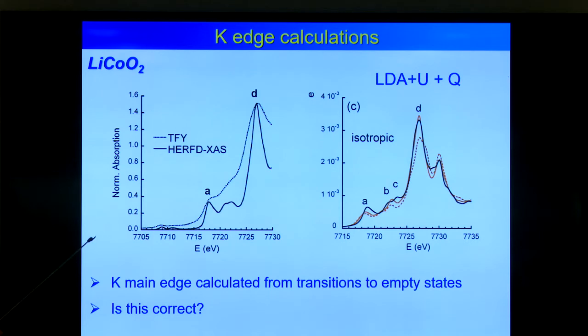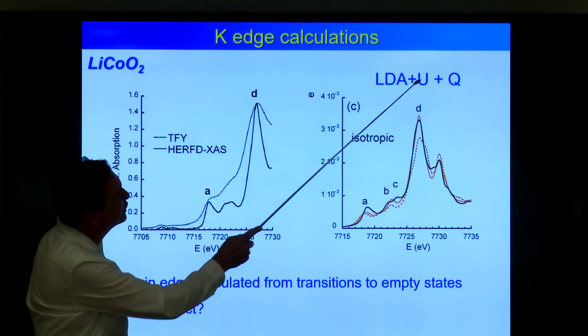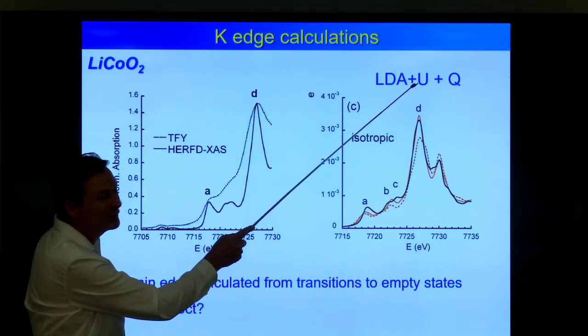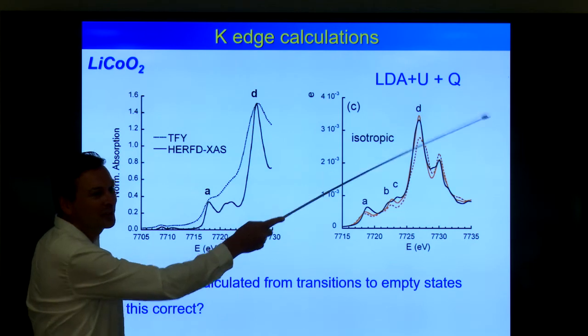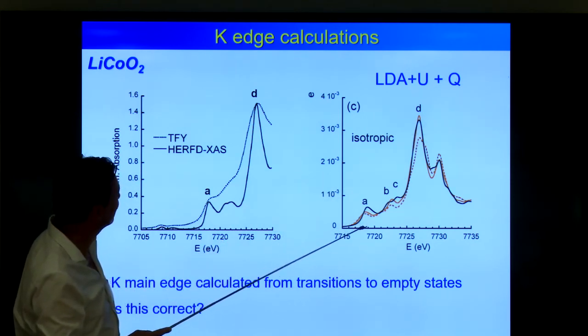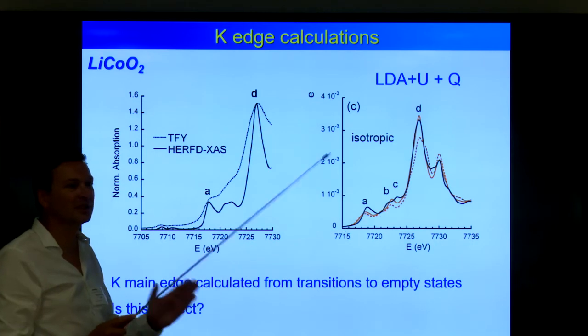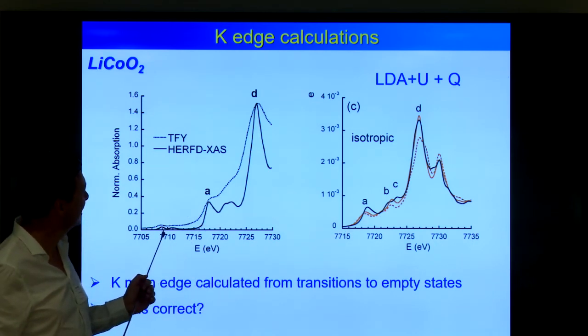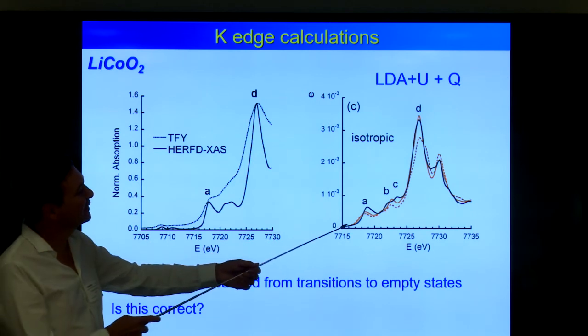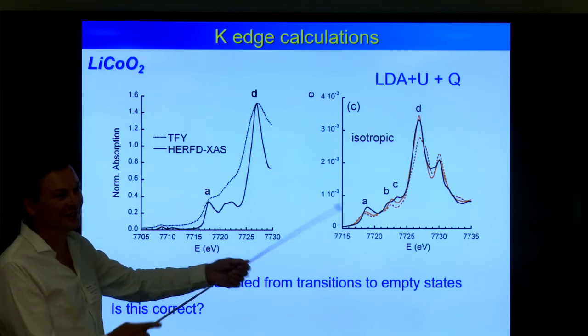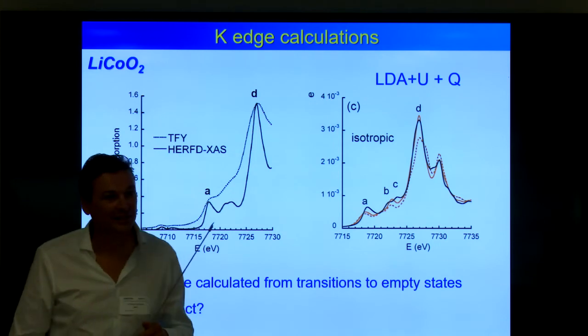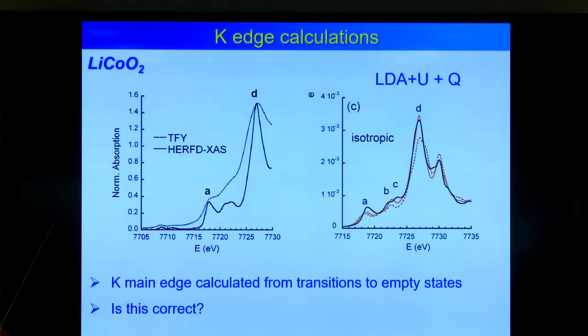Just a quick clarification in your notation. The plus Q means you've put in an estimate of the quadrupole matrix element? No. LDA plus U is the density functional code, and this is the core hole potential. So we put in the core hole. Got it. Yeah, we put in the quadrupole. Now we do separate calculations. We do quadrupole for the pre-edge, we do with multiplets, and the dipole we do for the edge. We do not mix it. And just to go back to the partial versus full core hole, what's the choice here? This is full core hole. Okay.